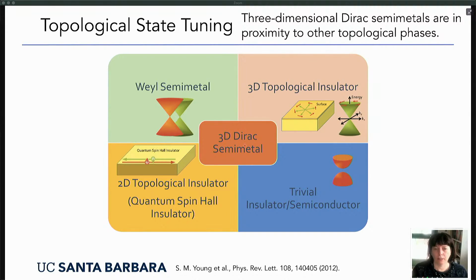But from what I already alluded to with breaking symmetries, a very interesting property of these Dirac semimetals is that they're actually close to a number of other topological phases. So as I mentioned, for example, if you open a band gap, you very often get a three-dimensional topological insulator state. And what is a three-dimensional topological insulator? That's a material where there's a band gap in the bulk, but the surfaces are actually conducting. And the surfaces, again, you consider them to have Dirac nodes on each of the surfaces, and interesting properties such as the spin momentum locking that I've tried to indicate here.